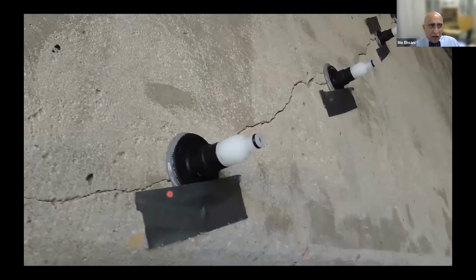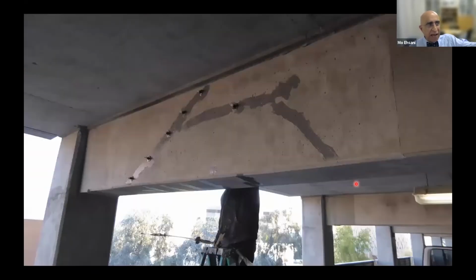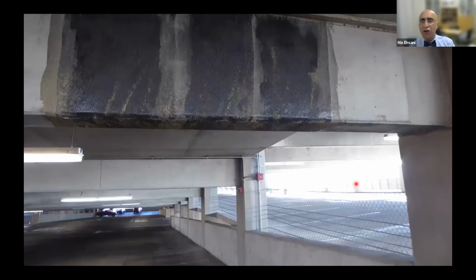Of course, if the concrete is cracked, it may require some crack injection. Here, we are doing first the crack injection in the concrete, realizing that the crack was formed because of lack of steel. Following the crack injection, we could apply the carbon fabric to provide additional strength for those beams that were weak.